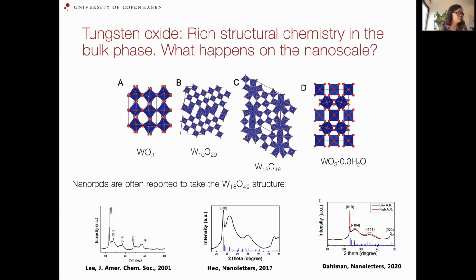This is an older version, but also in recent high impact literature, showing their XRD patterns from these nanorods, as well as the reference compound, which is W18O49. So it's this structure here. And when you look at this, this is the calculated pattern, right? The way this is usually done is just to compare where peak positions are.